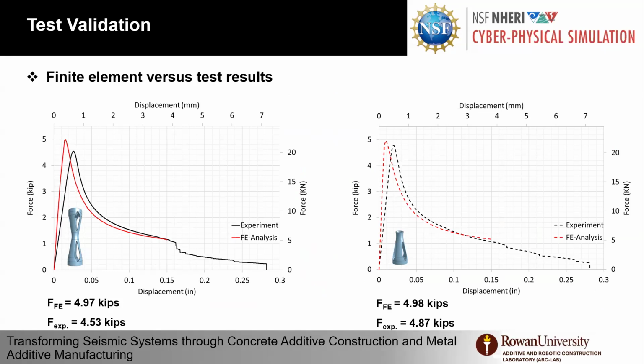We did not. We did SEMs to see what kind of imperfections we have, and we do have some uncentered elements or not fully melted particles that may create voids, and that actually could contribute to the high stiffness in the finite element compared to the actual test. We were not able to quantify it because we don't have the history of the print as we printed. However, we do have the digital image correlation data.